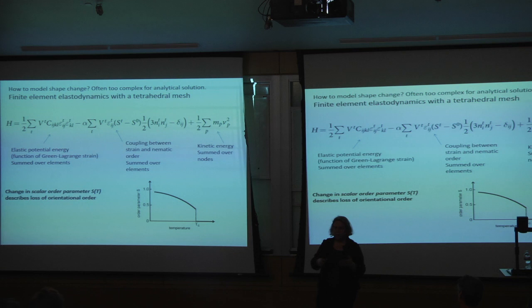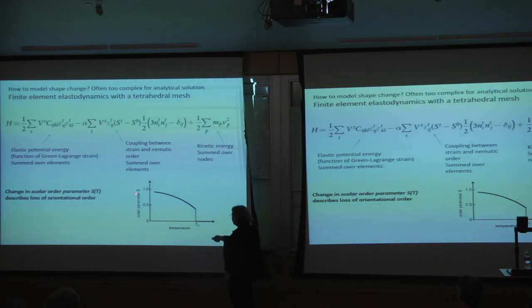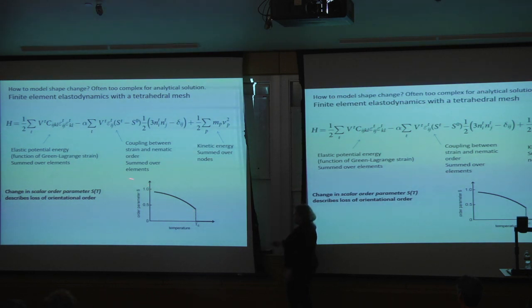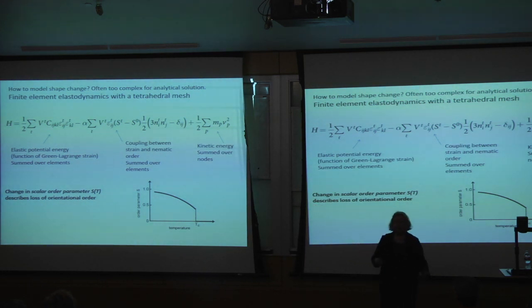So in a liquid crystal, when you heat it, this is a graph of the scalar order parameter as a function of temperature, and at the isotropic nematic transition, it drops to 0. That's a measure. So at lower temperatures, it's ordered, but it gets less and less ordered and then goes to 0. So in our material, we know as we heat it, the nematic order is changing. This term couples strain and nematic order such that when you heat it and the scalar order parameter drops, the material shrinks along the nematic director. And that happens because there's a coupling between the strain and the state of nematic order. But I will skip the mathematical details.